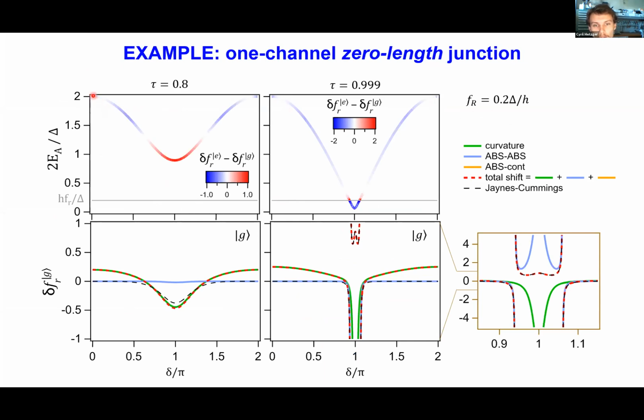First, when the transition from ground to excited state is strongly detuned from the resonator, and in the second case where it crosses it. So in the first case, because the qubit and the resonator are not on speaking terms, the exchange of photons with the resonator is strongly suppressed, and so the contribution to the shift from virtual transitions here in blue is almost 0. And so the total shift experienced by the resonator in red is almost entirely given by the curvature of the ground state.